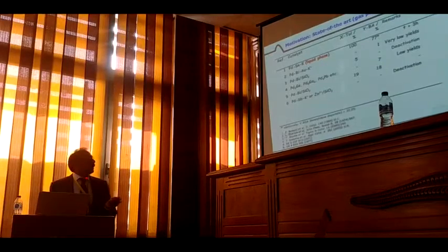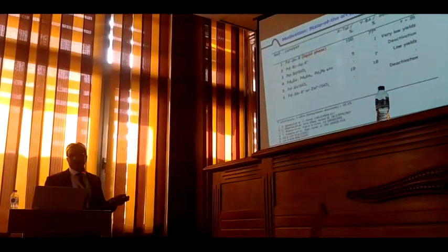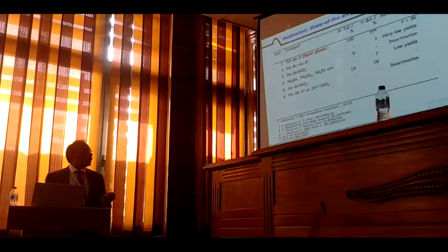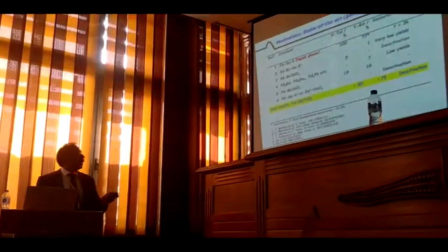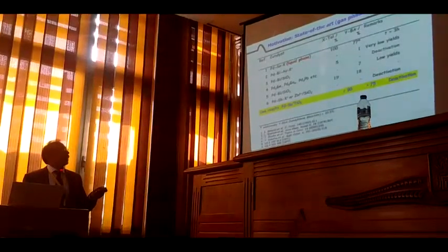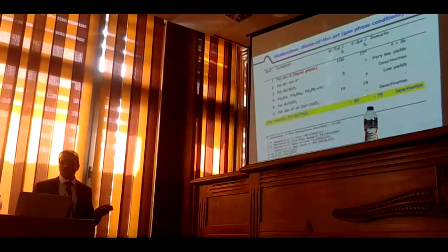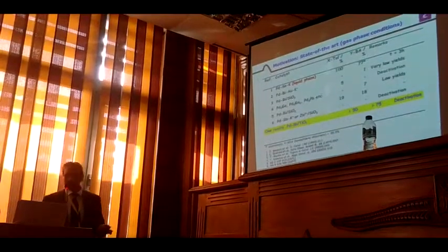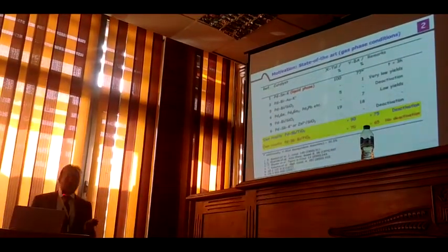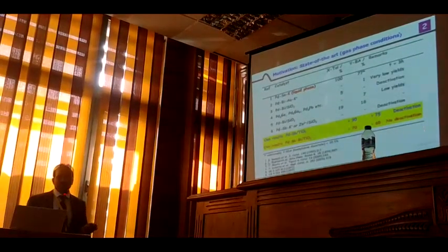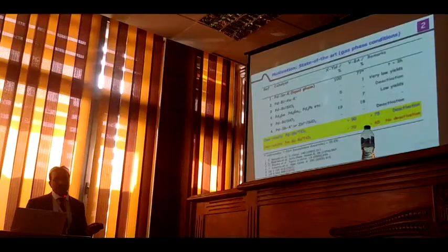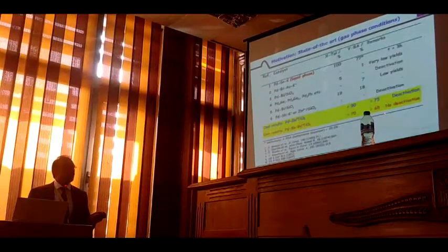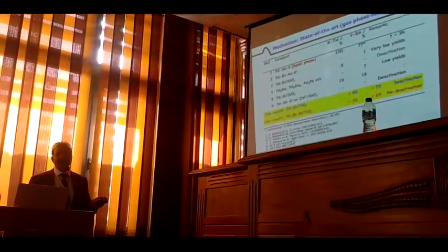The first point. And second is, palladium is widely used. It's there everywhere. So, we have made efforts to develop catalysts, also using palladium and other composition. And we were able to reach more than 90% conversion and more than 70% yield of benzene ester, which is really good achievement. But we still have the problem of deactivation. So in subsequent efforts, by modifying the catalyst composition, we were also able to prevent the deactivation successfully. But we lost some activity. Doesn't matter. The activity is lost, but this is somewhat compensated by the enhanced selectivity. Here the selectivity is more than 95%. Here you have between 80 to 85.